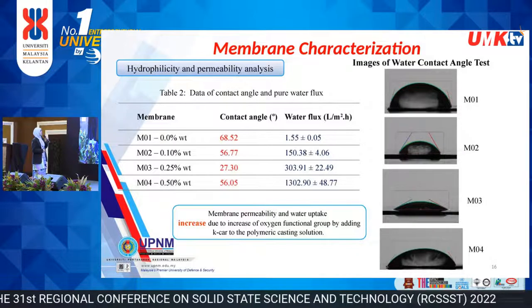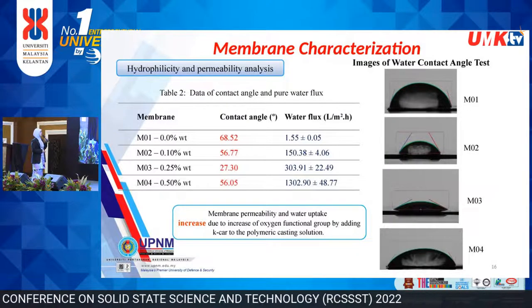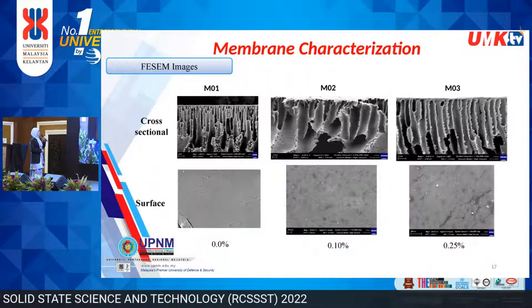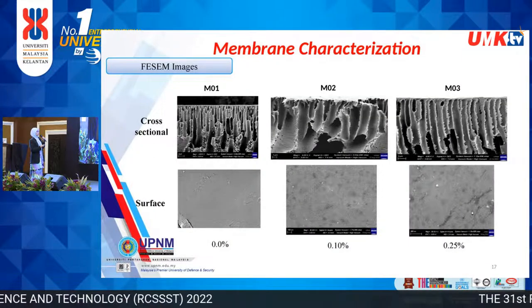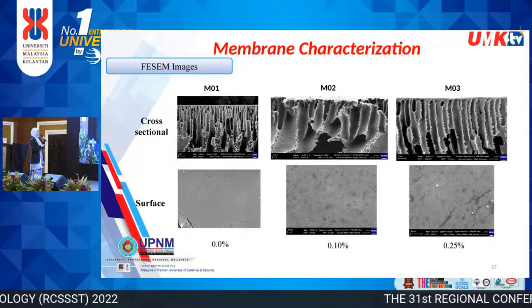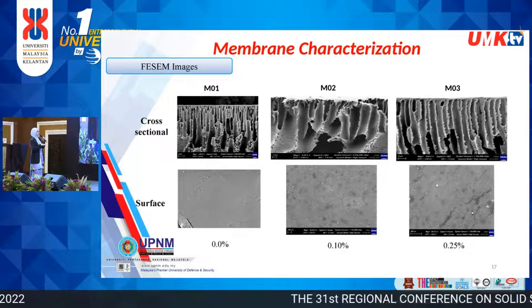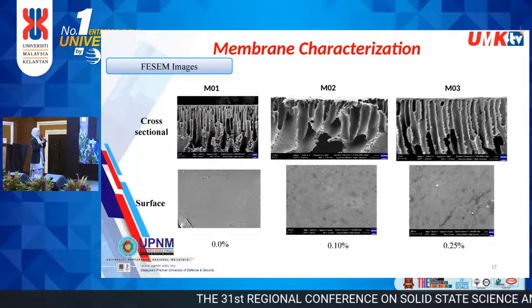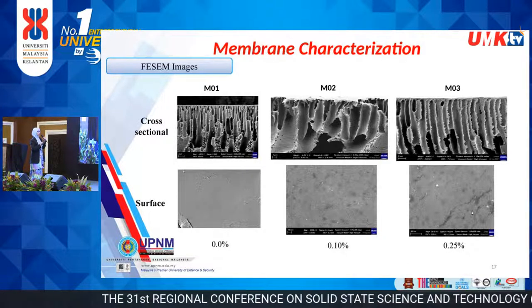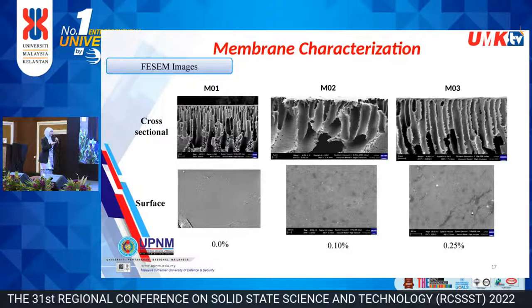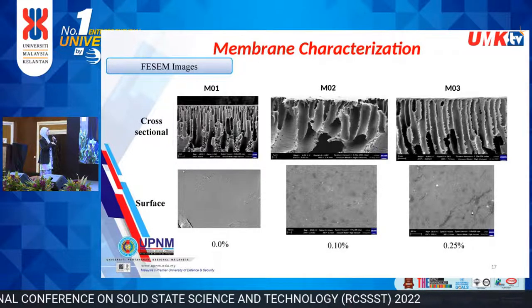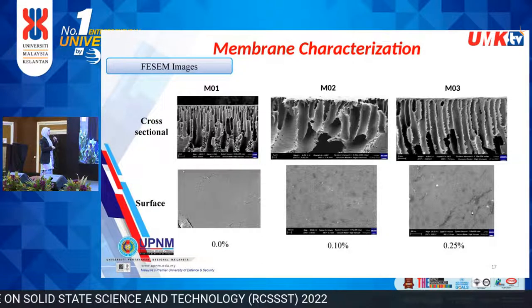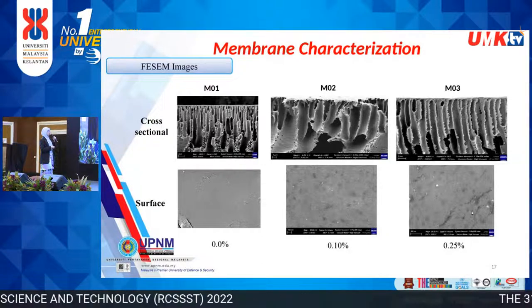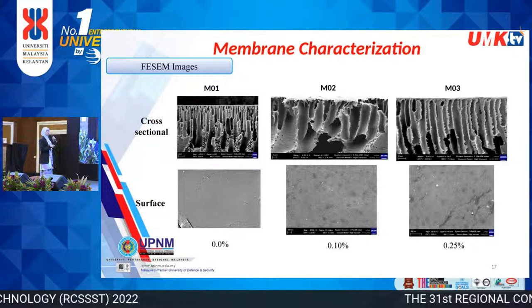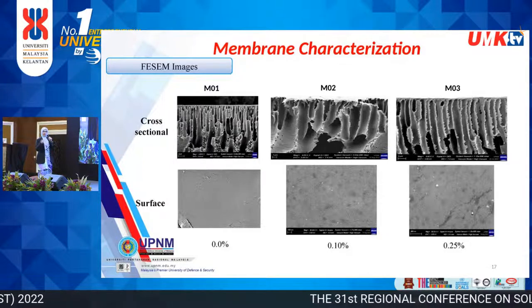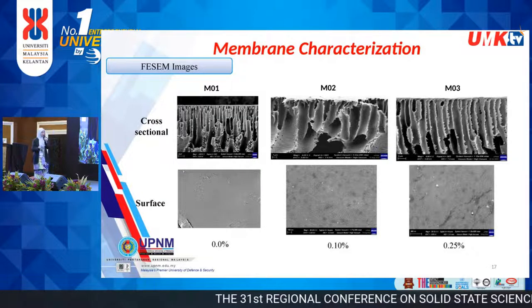All right, so these are FESEM images. This is just to show and compare the pure polysulfone membrane and the membrane to which we added kappa carrageenan. Basically, we still have a finger-like structure in the membrane. But we are about to check the porosity, and that will be presented at the next coming conference, maybe.